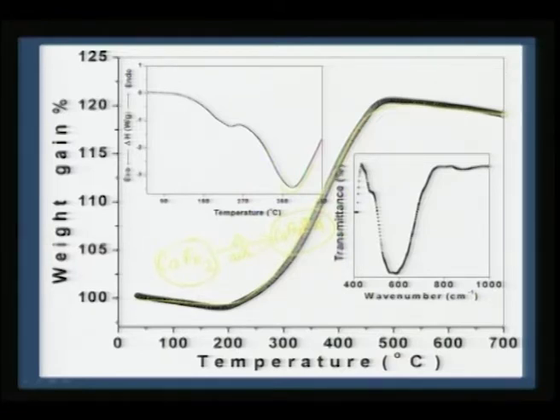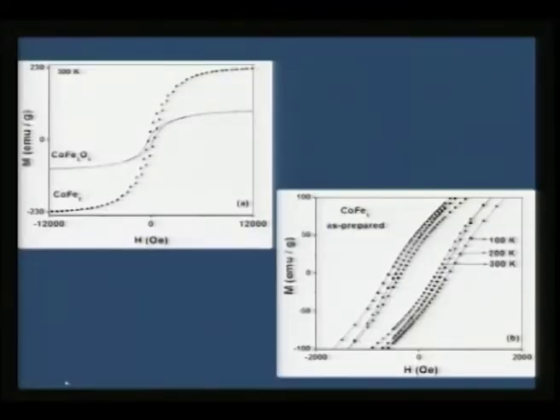So that is clearly seen in the DTA curves, and we also see that the formation of the oxide is pronounced due to this typical stretching which is observed at 600 centimeter inverse, confirming that the oxide formation is indeed correct. And we can also clearly distinguish between the alloy and the oxide powder.